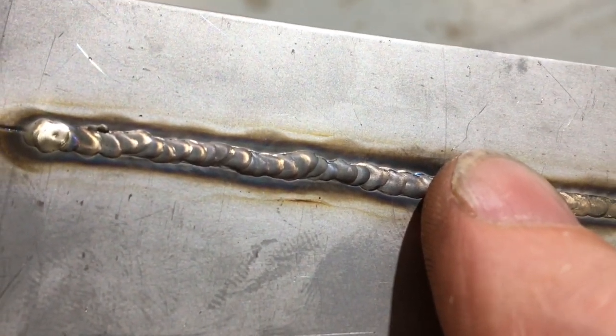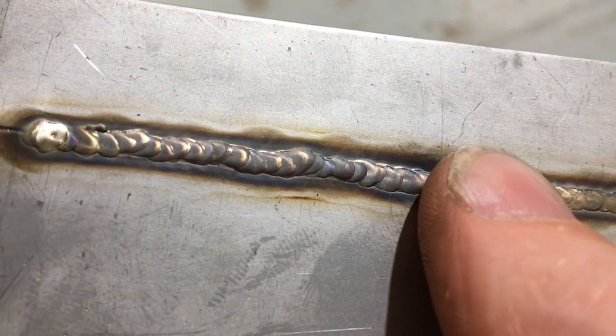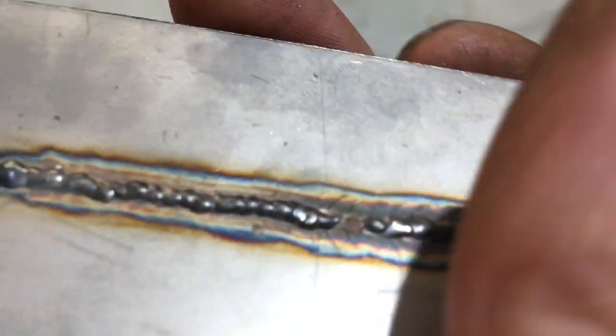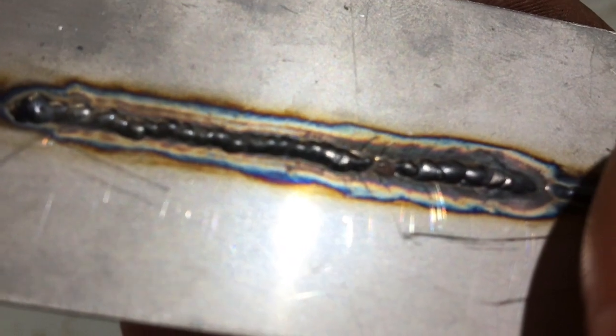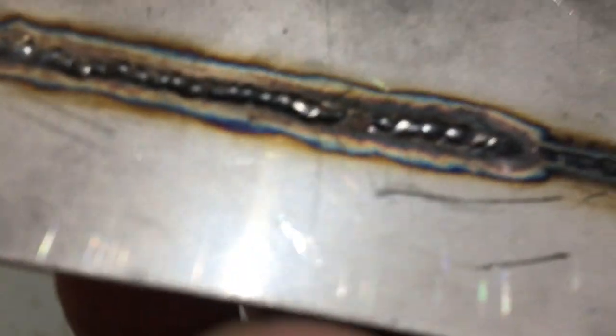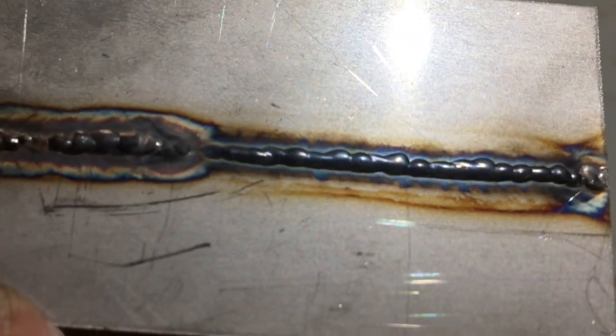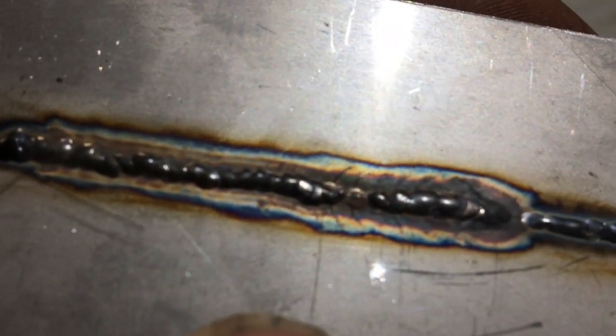Not necessary on 300 stainless. If you can't move, if you get in a bind, just stop. Looking at the other side now, it's clear that the heat affected zone is much wider on the part that was welded more slowly. So it's a good example of the less amps, more heat phenomenon, if you like.